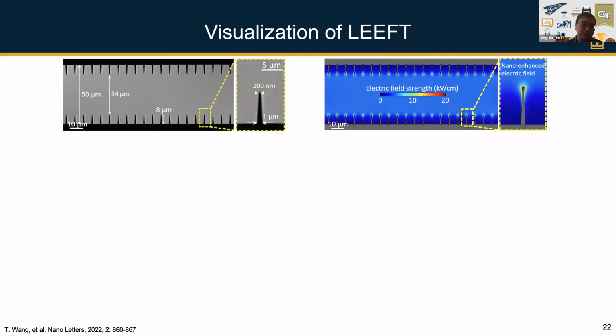So just to show you some results. This is again the chip we made. We also studied different systems with different diameters, but we ended up with the optimal design of this chip here. And this is a simulation to make sure we can calculate what electric field strength we can achieve. We do demonstrate that, at least based on a simulation, near these tips the electric field strength can be several tens of kilovolts per centimeter, which is theoretically required to achieve irreversible electroporation to kill the bacteria.